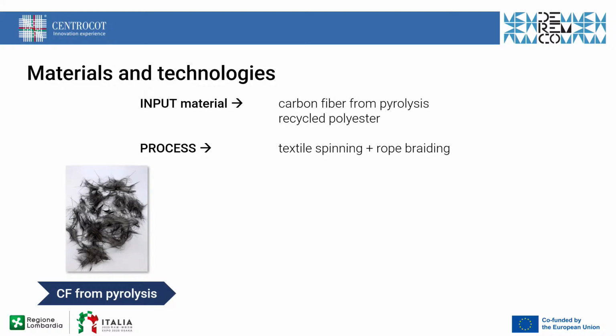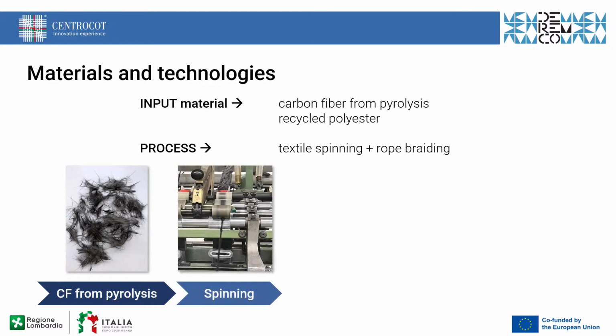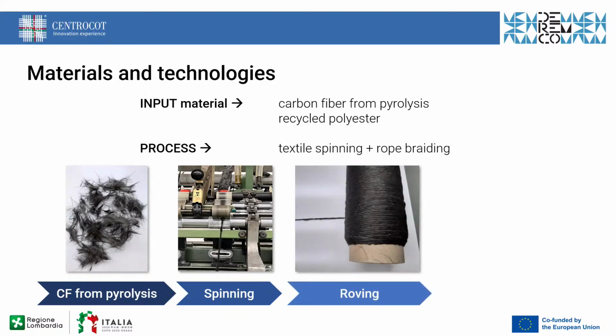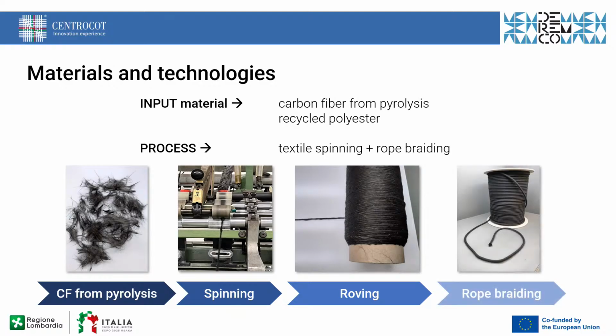carbon fibers. So we decided to mix them with recycled polyester and applied all the technologies typical of the textile spinning. So after mixing with a different composition, we did the spinning, we obtained a sliver and later a roving. But for this material to be used for a practical application, we decided to embed it into a polyester rope in order to have some practical applications and avoid contamination and the release of the fibers during the use.